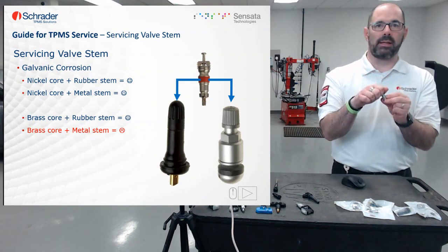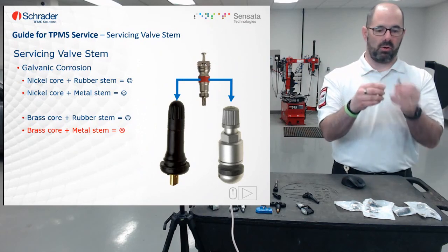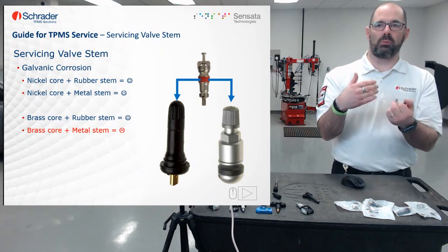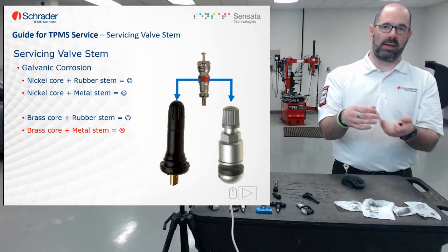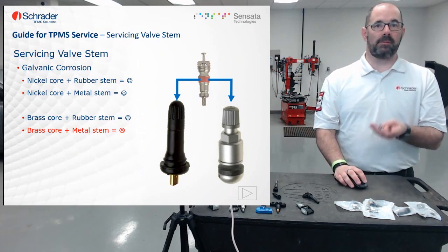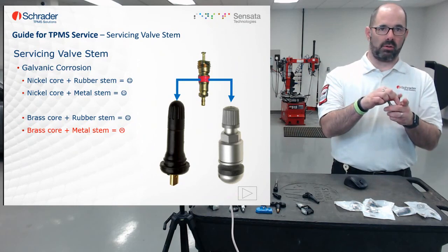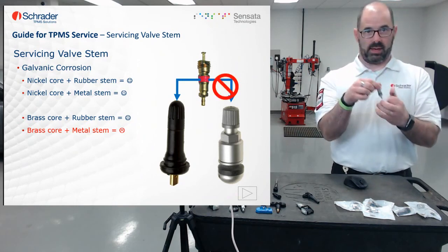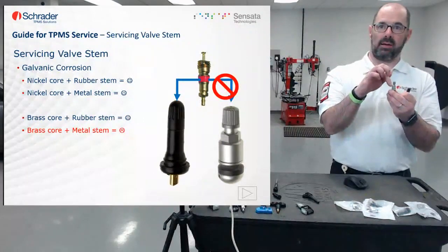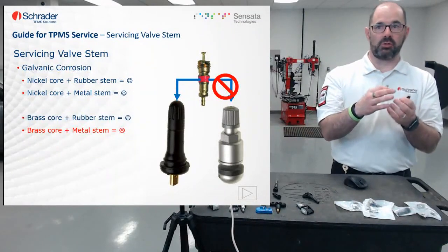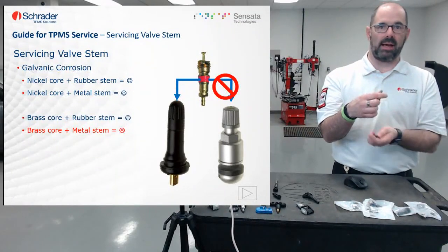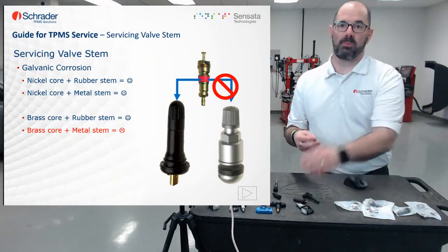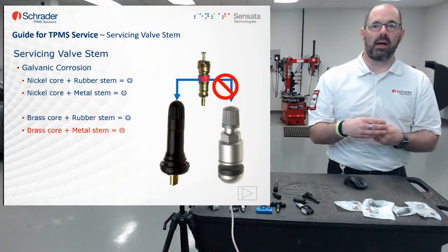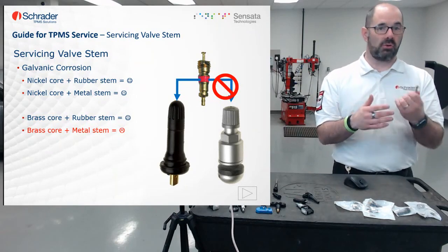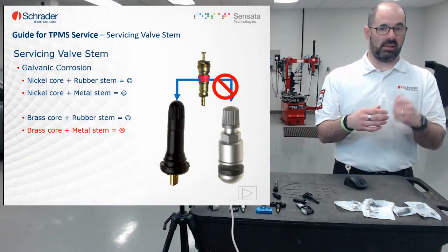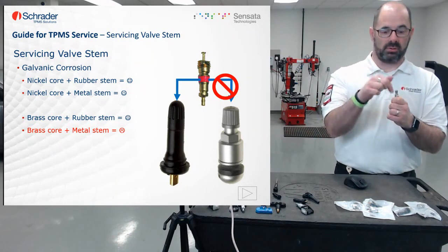Now, a nickel-plated core can go in either. The nickel will give you protection against galvanic corrosion. But if you put on a brass core that you took from a rubber stem into a metal valve, you're creating a potential issue for your next visit. You're creating that perfect combination for galvanic corrosion. So next time your client comes back for his tire service, there's a strong chance that you'll have a hard time just taking the valve core out of the valve.